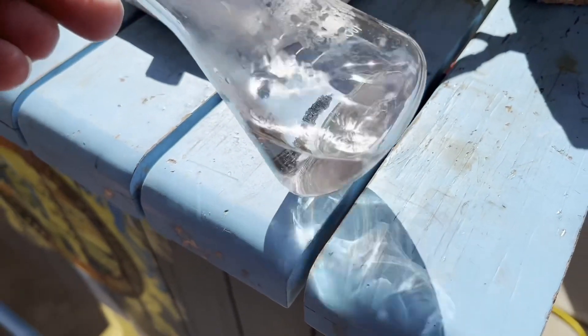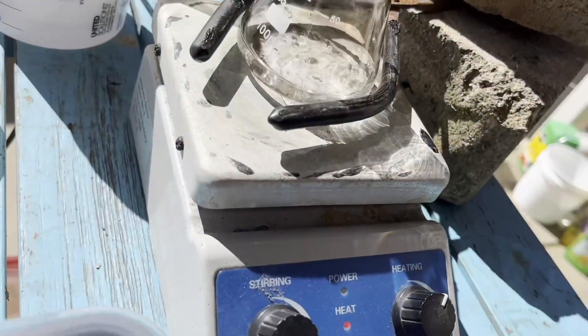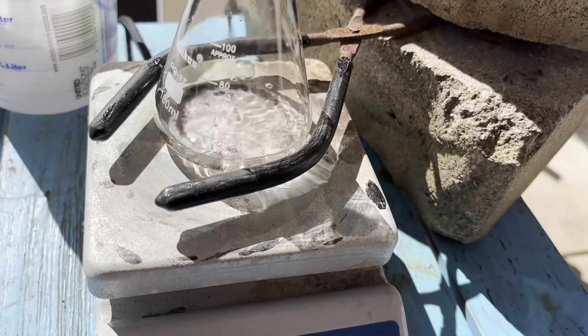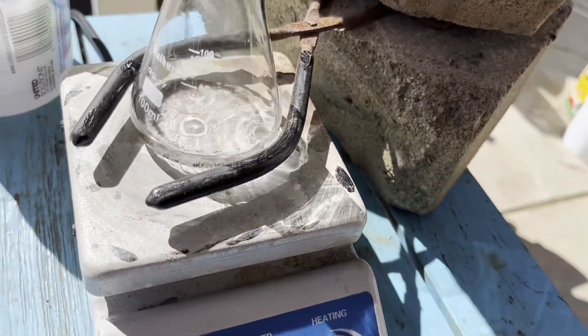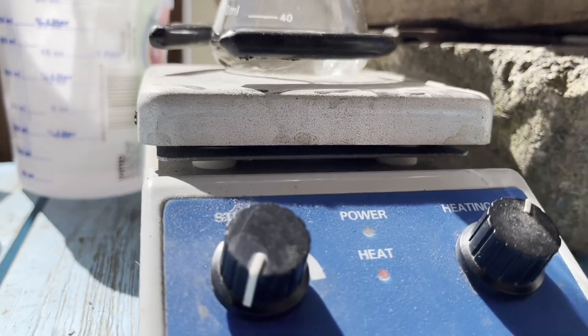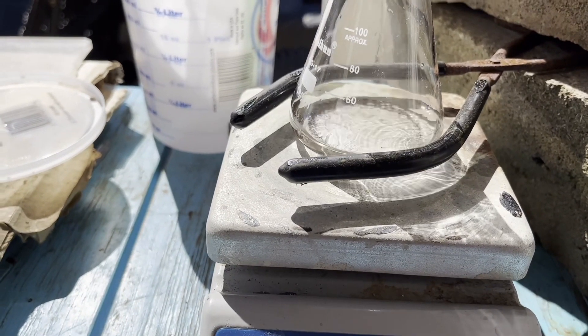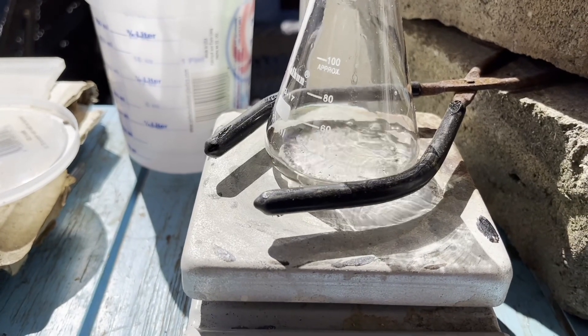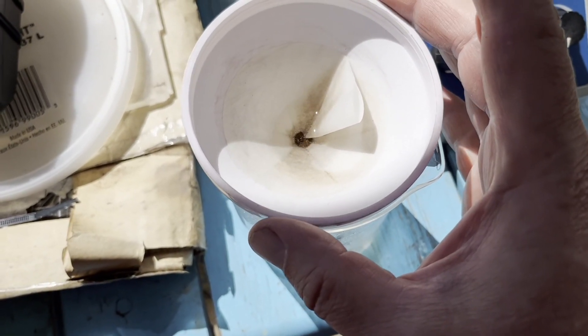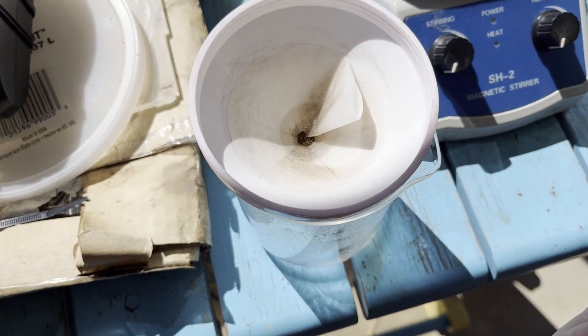Here's the first water boil — it's been boiling for a couple of hours. This is definitely a small, small batch amount. I see absolutely zero color in the hydrochloric acid, but I am restricting the oxygen to it also. I'll remove that cover plate and let it cook for a bit — with absolutely no color showing up in the hydrochloric acid, I'm going to consider that done. I'll dump the hydrochloric acid out, give it a hot water wash. When I tap it, it runs right down to the bottom — it's actually looking pretty good. This is the fourth water rinse.